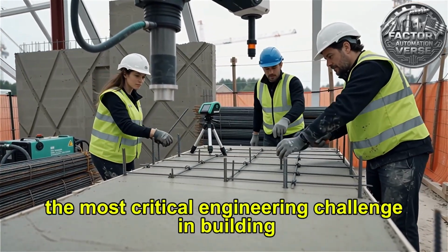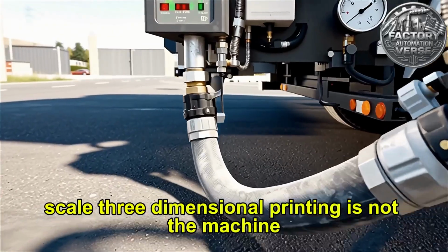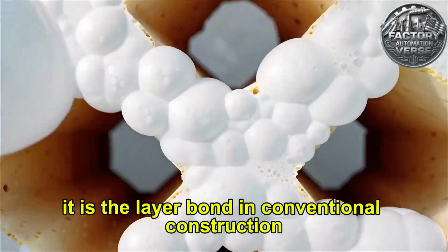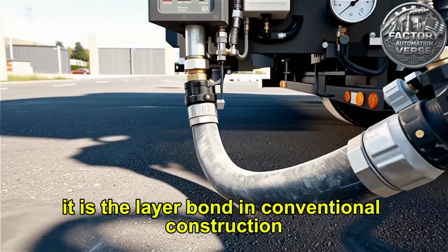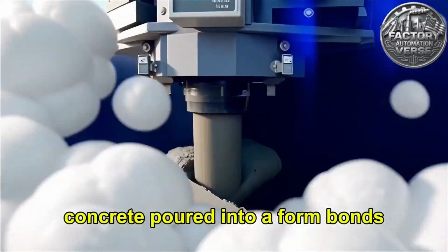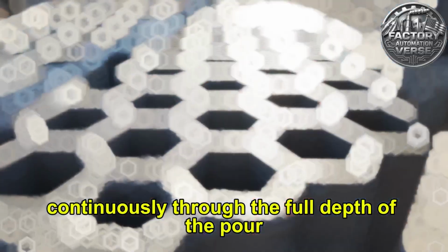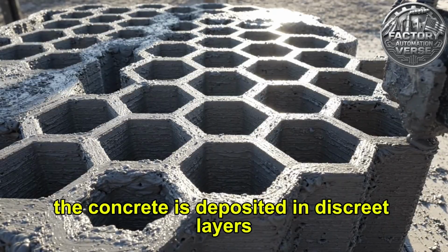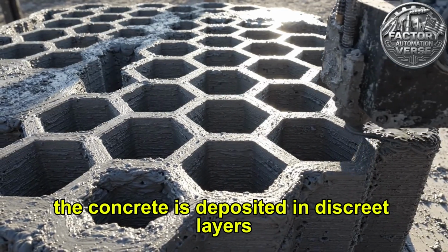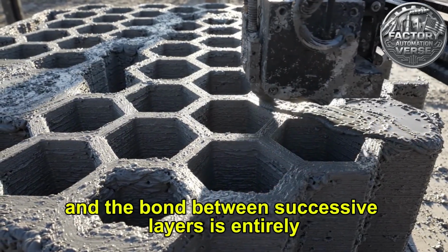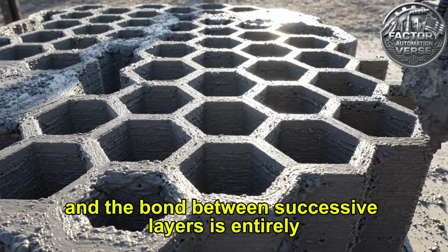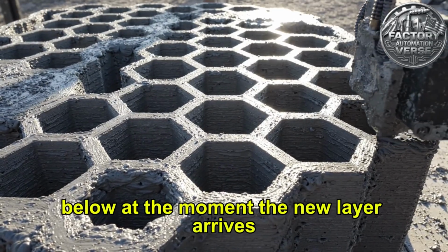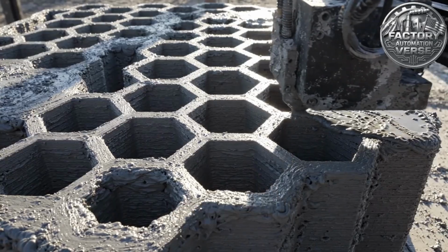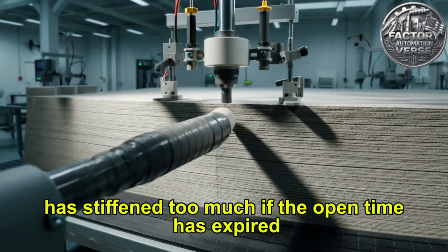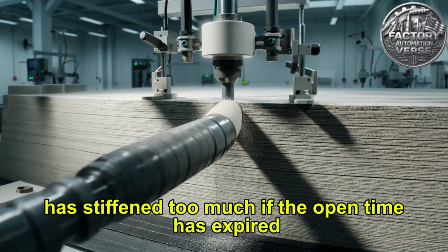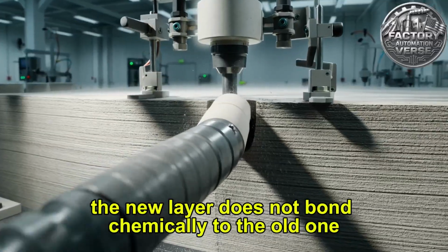The most critical engineering challenge in building-scale 3-dimensional printing is not the machine, it is the layer bond. In conventional construction, concrete poured into a form bonds continuously through the full depth of the pour. In a printed structure, the concrete is deposited in discrete layers, each one a few centimeters thick, and the bond between successive layers is entirely dependent on the surface condition of the layer below at the moment the new layer arrives. If the previous layer has stiffened too much, if the open time has expired, the new layer does not bond chemically to the old one.